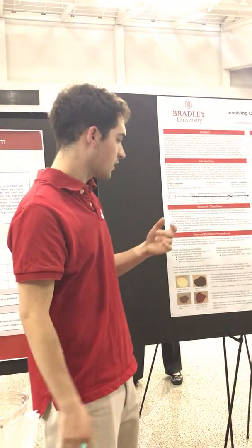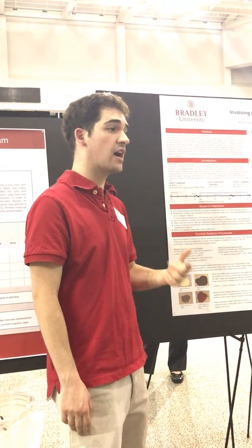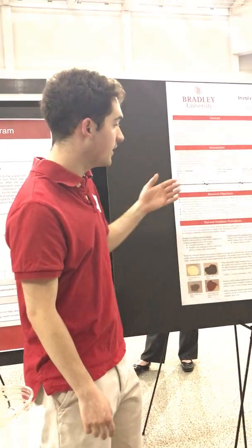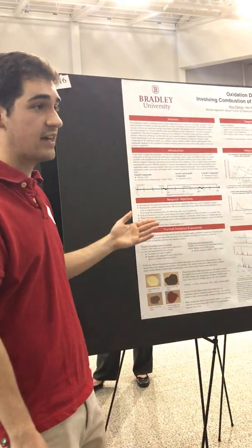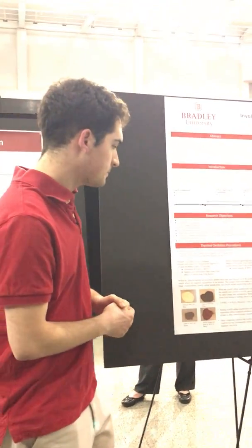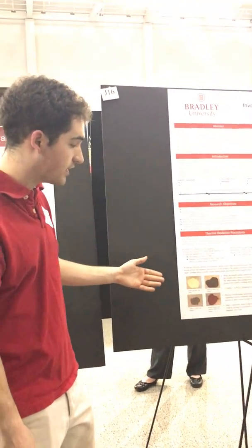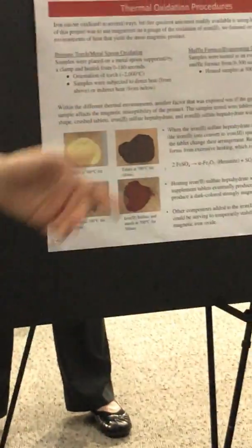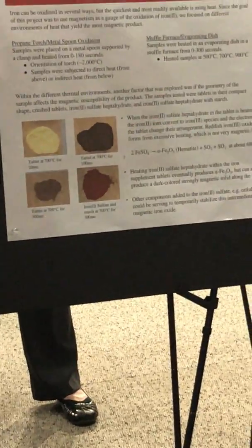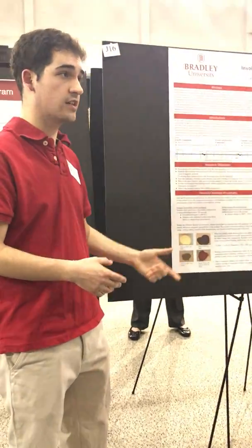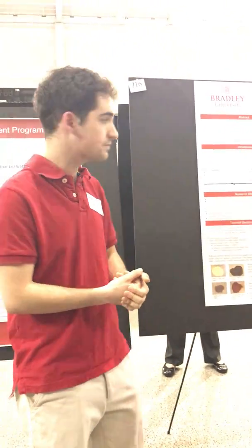It's well known that if you heat just iron 2 sulfate, it goes straight to hematite, that non-magnetic iron 3 oxide. Some preliminary results we can see here: just like an iron supplement tablet, with increased heating it goes to a dark brown color, then to either a red or a purplish gray color. So we can use that color as a gauge of the oxidation.